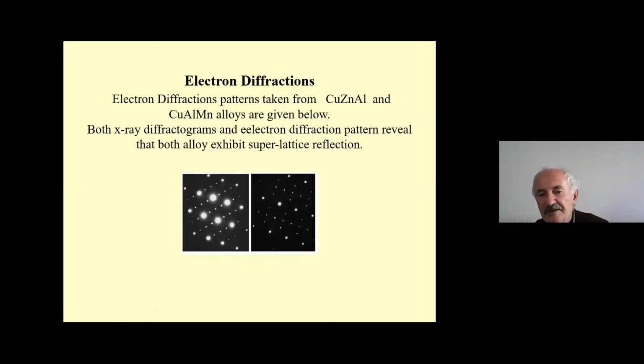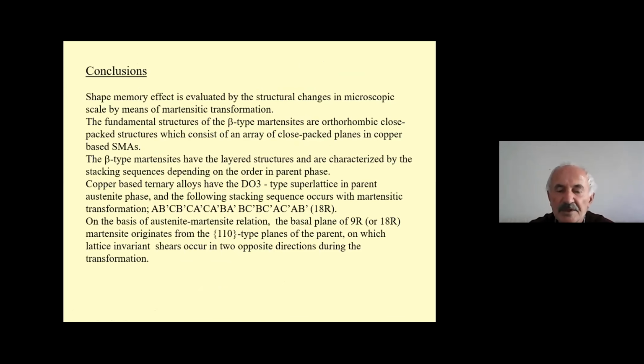Second, an experimental study is performed on electron microscopy. And as you can see, the electron diffraction pattern also exhibits superlattice reflections. Conclusion: the shape-memory effect is evaluated by the structural change in microscopic scale by means of martensitic transformation.